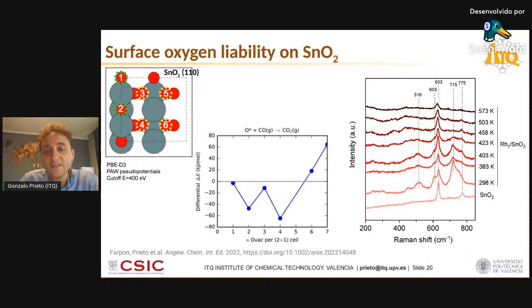We could indeed see very clearly the fingerprints for oxygen vacancies associated to the loss of this bridging type of oxygens, oxygen 1 and 2. We could never see, in the temperature regime which is relevant for our catalytic applications, any fingerprint for in-plane oxygen vacancies, meaning that the loss of this type of in-plane oxygen is insignificant compared to the loss of bridging type of oxygen under reaction conditions.